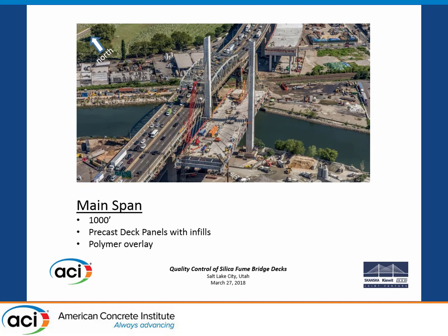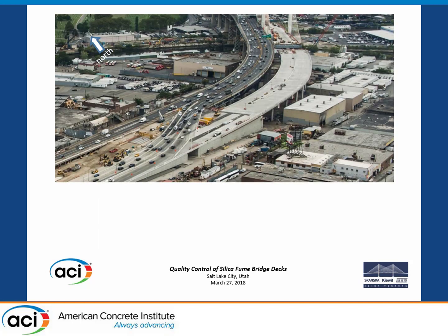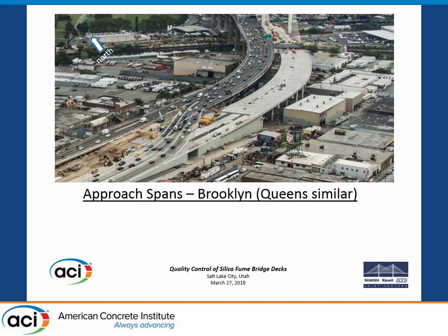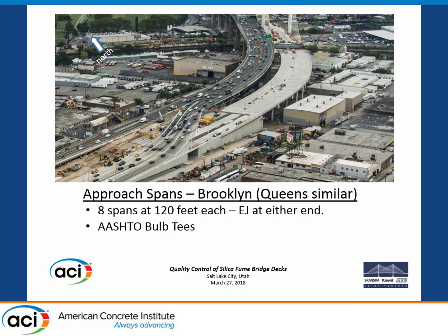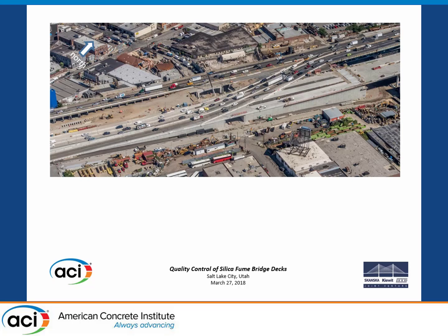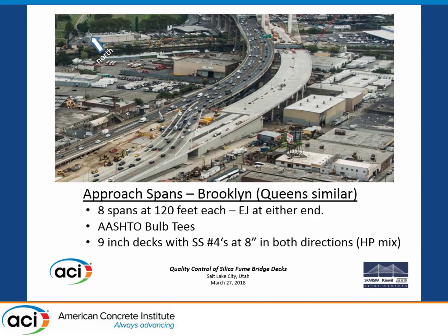Okay, the main span. It's 1,000 feet. It's precast deck panels made off-site, and then they've got infills between them. They've got polymer overlay. That went pretty well. This is the Brooklyn approach spans, 1,000 feet, at 8 spans, so it's 120 each. There's an expansion joint on either end, so you go 1,000 feet without an expansion joint. It's 9-inch decks with number 4s at 8-inch centers, both directions, and we use an HP mix. There's 2 inches of cover on the approach deck. I know I'm going fast.